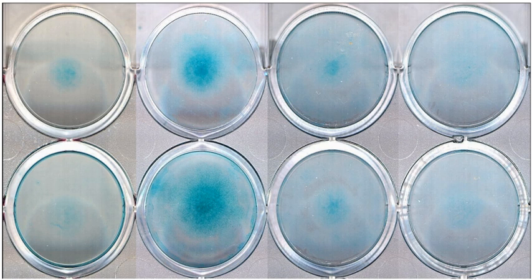Topic: Gas foaming. To overcome the need to use organic solvents and solid porogens, a technique using gas as a porogen has been developed. First, disc-shaped structures made of the desired polymer are prepared by means of compression molding using a heated mold. The discs are then placed in a chamber where they are exposed to high-pressure CO2 for several days. The pressure inside the chamber is gradually restored to atmospheric levels.